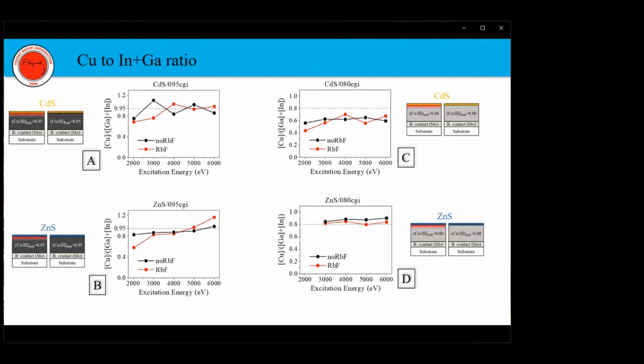This can be explained by a partial outleach of a copper species in the beginning of the deposition process into the chemical bath. So they probably form a mixed compound together with zinc sulfide. The RbF PDT did not lead to any significant variation in copper concentration in case of the copper poor sample. On the other hand, in case of the copper rich sample, copper atoms seem to be driven from the interface to the absorber as a result of PDT.